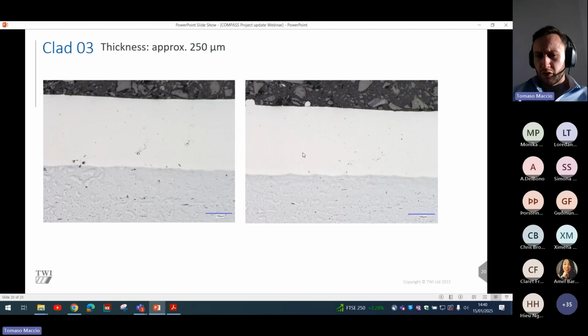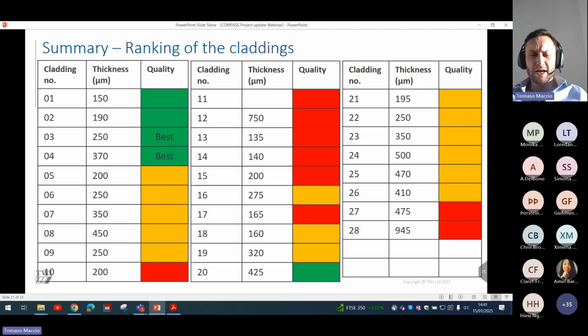And as I stated before, one of the main benefits of EHLA is the heat affected zone and the dilution of the weld. If this was a traditional laser cladding deposit, we'd have quite a mixing of the melt pool. So we'd have quite a lot of the substrate dragging through into the deposit. And what that's doing is dragging the iron that's in the substrate, which is obviously susceptible to corrosion, through the deposit, and making it less corrosion resistant. Apologies.